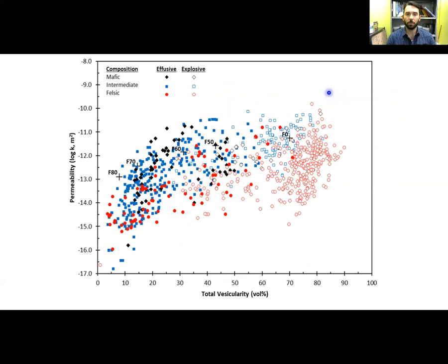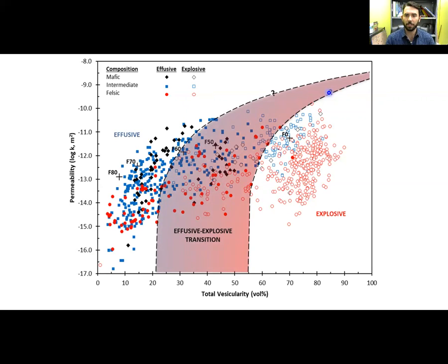We can now explain the controls on explosive effusive transitions and constrain its boundaries. Up to this point, this has not been possible without a comprehensive study testing the effects of higher crystal fractions on outgassing mechanisms. The transitional zone, which contains products of both eruption styles, is bounded by curves similar to the Kozeny-Kármán fits. This delineates a critical permeability above which magmas no longer pose explosive hazards. Magma can reach this permeability threshold either by a rapid increase in permeability due to fracturing or a decrease in porosity due to collapse of permeable pathways.